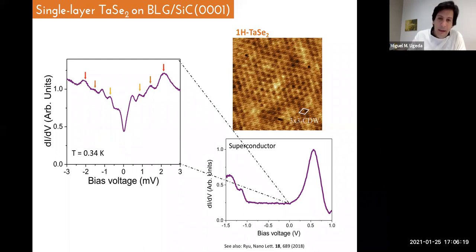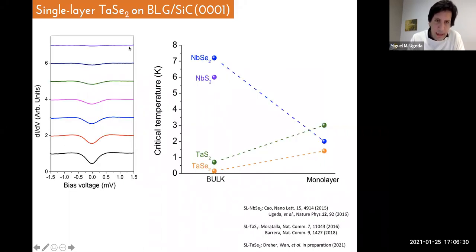In any case, something interesting about the tantalum diselenide, apart from the existence of these spin excitations, is that, I forgot to label this, but this is 0.1 and this is 1.4. So basically the superconductivity disappears at 1.4 Kelvin. But anyway, if you remember, I said before that the critical temperature of this material in bulk is 0.1 Kelvin. So with respect to the bulk situation, the critical temperature or the superconductivity strength is increased in the monolayer limit. And this is in contrast to the niobium diselenide case where it goes down. We don't know why, nobody knows why yet. There is a lot of room for investigation in this regard.